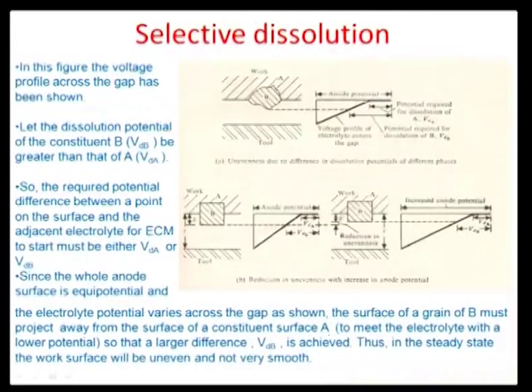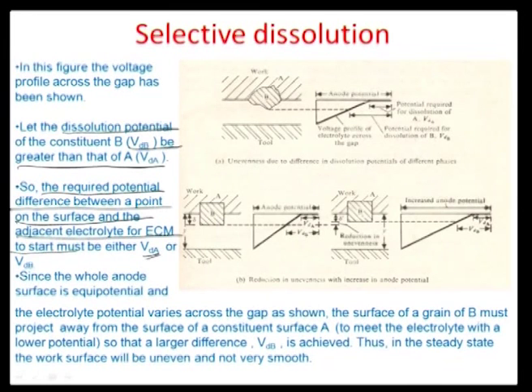So, if we assume that the dissolution potential of B, VDB, is greater than that of A, VDA. So, the required potential difference between a point on the surface and the adjacent electrolyte for ECM to start for the phase A must be VDA or must be VDB for the phase B. Okay, so, till and until this potential is reached at the surface, the dissolution will not occur. Similarly, if for the B phase this potential is not reached, the dissolution will not occur. Now, what is interesting here is to see that because VDA is lower than VDB, this is, let us say, the anode potential, and this much amount is corresponding to the potential drop.